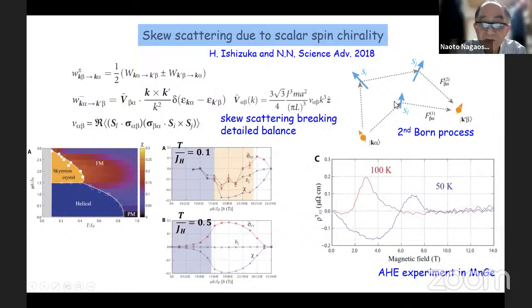Then the interference between this single spin scattering and two spin scattering leads to the so-called skew scattering probability. Skew scattering means from k beta to k alpha, and k alpha to k prime, sorry, this one should be k prime. So this detailed balance will be violated. And then this skew scattering probability leads to the Hall effect in the magnets.